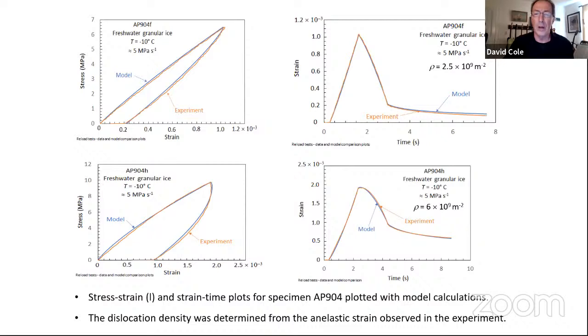So this is just a couple slides to show you. Again, the two things I've done here, other than plug in the temperature, is I feed the double load-unload ramp into the program and use that incremental formulation to slightly improve the fit. I did increase that peak width parameter from 0.54 to 0.6. That tightens it up a little bit. Seemed to give a little better response, but not hugely. But the only thing I'm really changing here is the dislocation density.